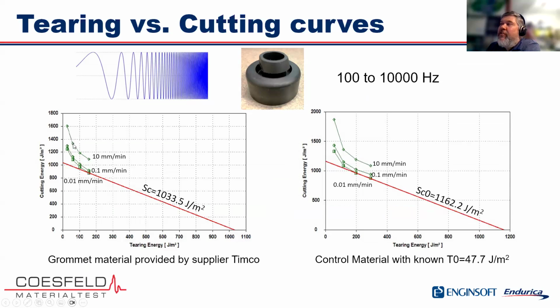The top curve is for the fast cutting rate. This was at 10 millimeters per minute. And then the next 2 curves are for the slower cutting rates, a factor of 100 and a factor of 10 smaller. And what's really beautiful here is that these 2 curves are almost on top of each other, which indicates to us that this is a good measurement, that's close to giving us the threshold.